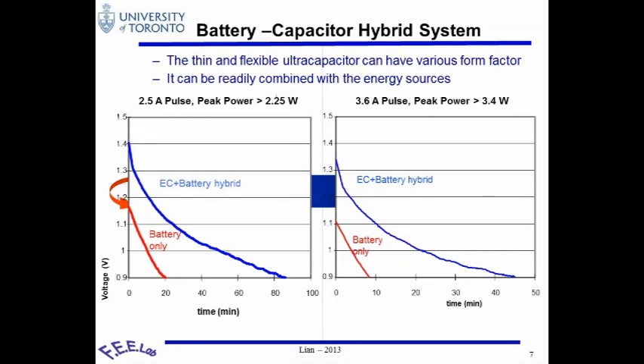What you see here, on the left side, are two graphs. One is battery only, so it's constantly pulsing at about 2.5 amp current, and then you can see it's pretty much died at a cutoff voltage of 0.9 volts at about 20 minutes.